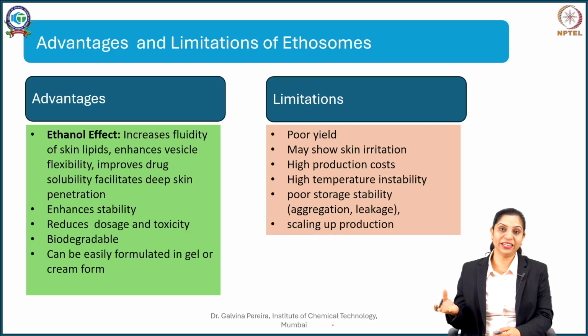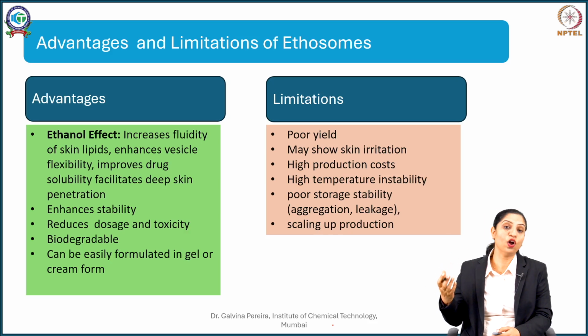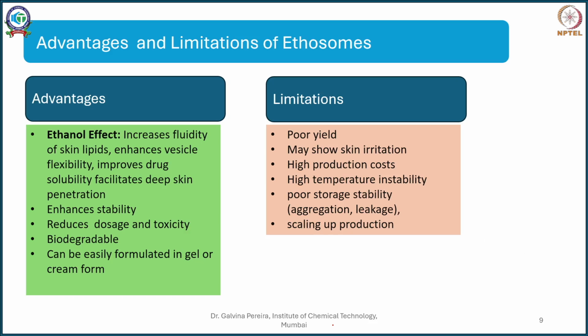Now this is, like I said, compared to other drug delivery systems, but as compared to your liposomes, your ethosomes are much more stable. For ethosomes, scale up is still a challenge because when you want to do particle size reduction, you need to do a number of passes, and this cannot be done on a large scale because it clogs the membrane and gives a huge back pressure, and better methods still need to be developed. But as liposomes are entering the market with HPH, definitely this is made a little more manageable.